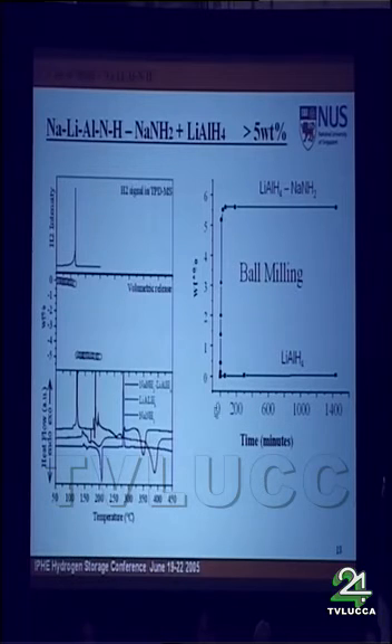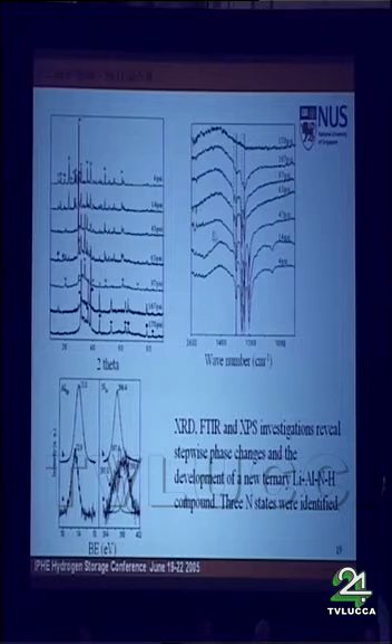Many interesting features are involved in such chemical reactions because we investigate the ball milling process of these two chemicals. We put these two chemicals into a planetary ball mill and stop the ball milling at different time intervals, collecting samples for X-ray and FTIR investigation. We notice there's a stepwise phase transition during such a chemical reaction. We also identify a new lithium, aluminum, nitrogen, hydrogen solid residue formed after the reaction.